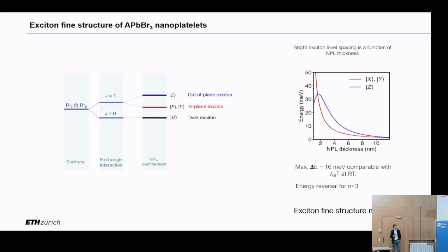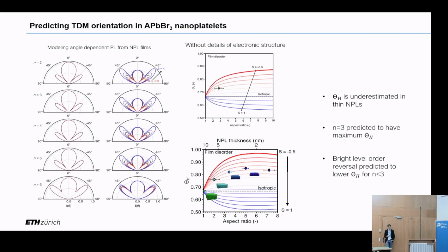And a very interesting thing happens at very low thicknesses below n equals 3, where you have an effective reversal of the order of the states, which means that here the blue, the out-of-plane exciton, actually is energetically favorable in very thin nanoplatelets, and this has to be taken into account by the model. And here I can conclude by just presenting how we can put all these ingredients together to try to understand what are the factors and try to predict the emission anisotropy from thin films of lead halide perovskite nanoplatelets. And you can see this was the picture disregarding electronic structure. This is the picture utilizing the full details of the electronic structure. It doesn't change very much at high thicknesses, where it's weakly confined, but there is a big change for very thin nanoplatelets.